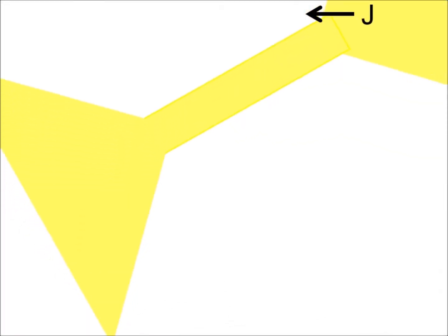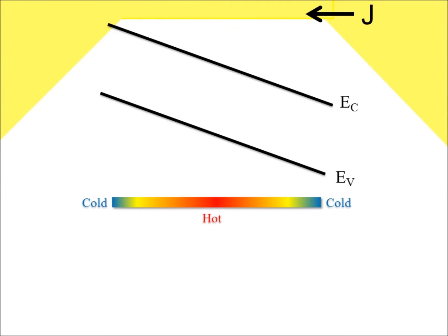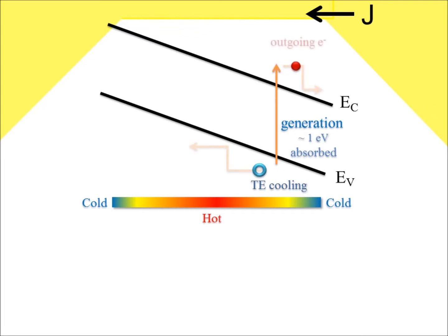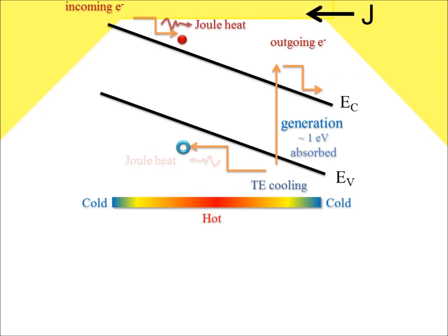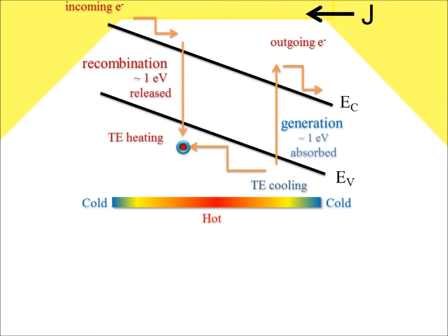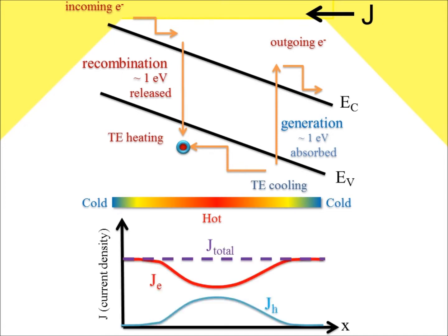This process is illustrated on a simplified energy band diagram of a wire. Generation of electron-hole pairs takes place in the hotter region, yielding energy absorption from the lattice. Electrons and holes are then separated and drifted by the electric field, causing Joule heating, which is the main heat source. The excess holes recombine with incoming electrons on the other end of the wire, yielding energy released to the lattice. The total current along the wire is constant and dominated by the electron current at the cooler regions, whereas the hole current is significant at the hotter region. Due to this asymmetric heat generation, the hottest spot shifts to where the minority carriers leave the wire.